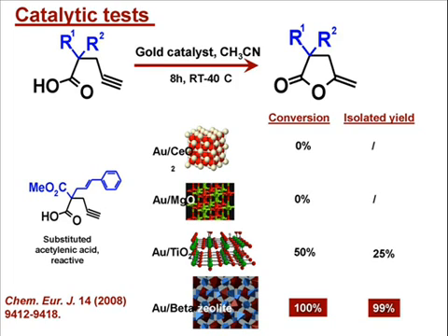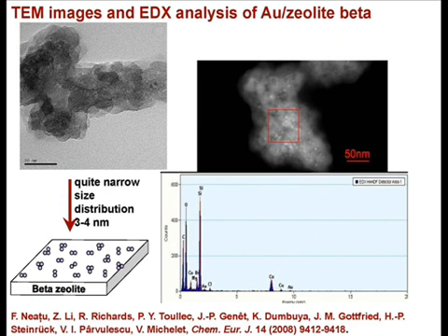Yeah, the story was, if you look at the electron microscopy, you have to have a very narrow, certain size distribution of the gold particles. Because you know very well from the literature, when Haruta is speaking about CO oxidation, and Graham Hutchings, the same, they are saying, okay, you have to have this size. When Avellino is looking for the oxidation of alcohols, also on gold, almost on the same support, it has different sizes when comparing with the size proposed by Haruta for CO oxidation.